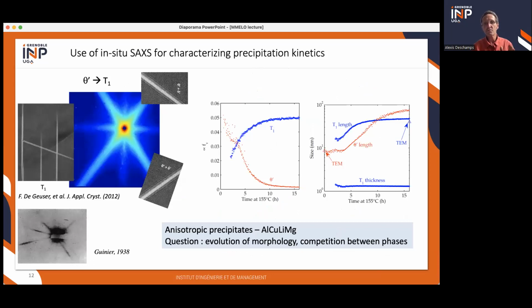So you can go to a bit more complex systems where you have the competitive precipitation of different phases. One example that I want to show here was in aluminum, copper, lithium, magnesium, where you have the competition between two precipitates, theta prime as platelets and T1 as other platelets. This characterization by SAXS with platelets was actually the first application of small angle scattering, by André Guinier in 1938. And using this technique he was able to understand why there was a strengthening in duralumin due to the presence of GP zones.